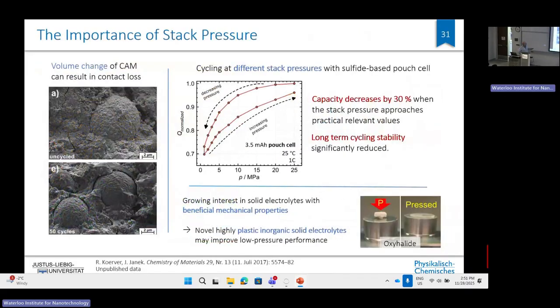Okay, and that's showing how important pressure is. And I think not only how important pressure is, but how depressing it is in a sense, because still today, you need quite some pressure to get good charge out and into your cell. So with increasing or decreasing pressure, the charge you can get out of an electrode really changes quite a bit. There is already quite some success with less pressure sensitivity of the electrode, but I think this is still a key issue. And if you ask, for example, EV producers that are honest, they would say, of course, a solid state battery should have the same stack pressure as a liquid-based battery. And that is virtually atmospheric pressure, or maybe just 1 bar or something like that, 0.1 megapascal, but not 100.